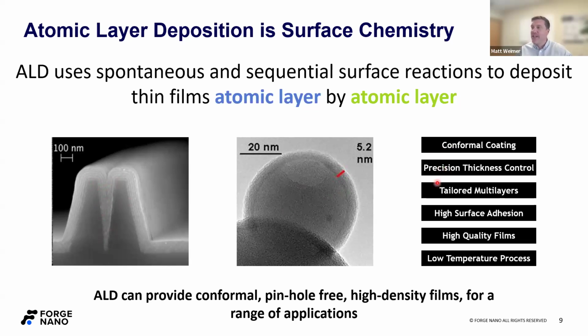I've already talked about precise thickness control. But one of the things that comes out of that are what are called multi-layers. We also call them nanolaminates. And that's shown on the left here, where two dissimilar materials are actually separated in layers. It's a really interesting way to tune bulk film properties. Some examples that I'll talk about later are, as an environmental barrier, doing this laminate scheme reduces the permeation of water and oxygen by orders of magnitude. You can also tune dielectric properties. You can think about reducing leakage current by putting in a low leakage material in a sort of higher leaking material. So there's a lot of games that we can play and a lot of interesting stuff.